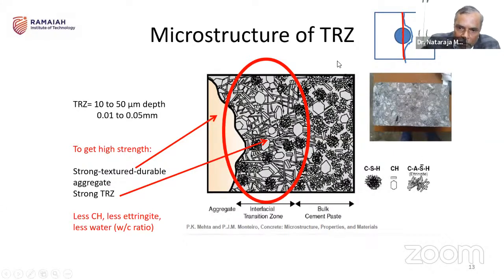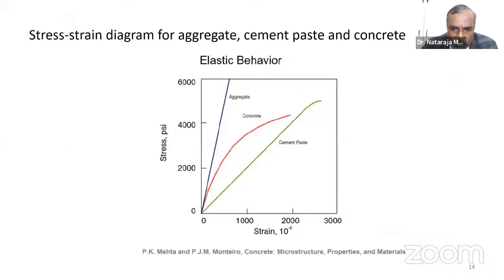So the condition you have substantially away from the transition zone, the same feature you will be bringing in very close to the aggregate phase. And that is the good phase, the strength phase, which is embracing the concrete. So with this, the compressive strength of the concrete increases to the extent of about 30, 40, 50 megapascal. This is what we have seen in many of our research. And one more interesting thing, which I have taken from P.K. Mehta's textbook, kindly see here, the relationship between the stress strain of the individual ingredients I am giving here.